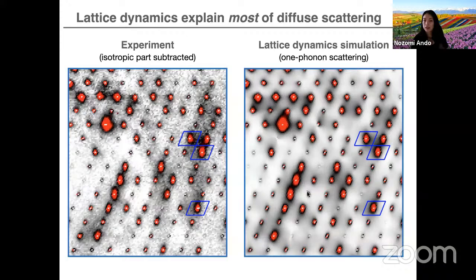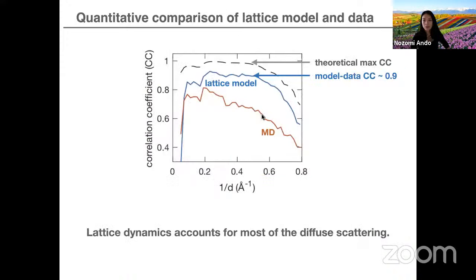And this was disturbing to us because the field had for a long time felt that this diffuse, cloudy pattern was due to protein dynamics alone. But what we were finding is that lattice dynamics actually explain most of the variational diffuse scattering. So that was actually a huge disappointment, yet it was still a huge accomplishment in the sense that the lattice model did a much better job than the MD at explaining the diffuse scattering.